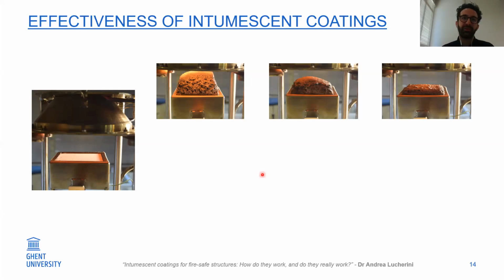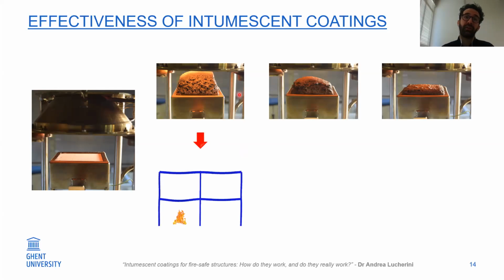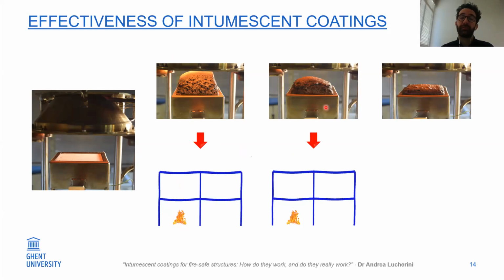And this is very important for your structural implications, because you can imagine if you have a coating that swells a lot and it creates a thick char, you can see that the temperature in this beam that is exposed to fire is not going to increase much, so you're going to have small displacements in case of fire. In the case that the coating swells a bit less and it insulates the steel beam a bit less, you can see that here the beam at this point will deflect more.